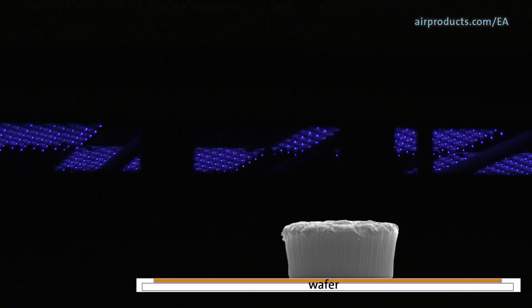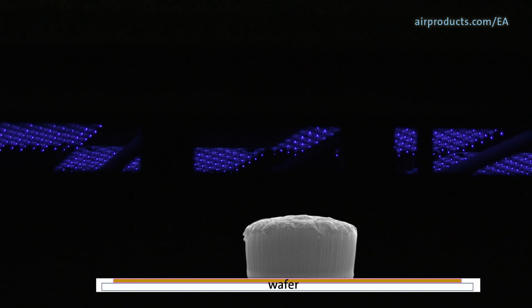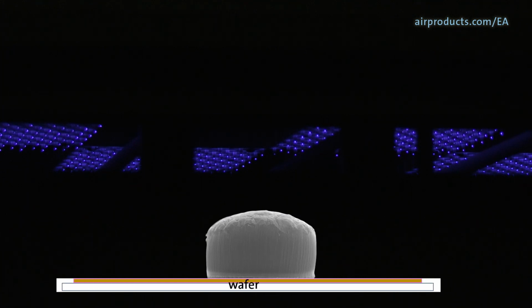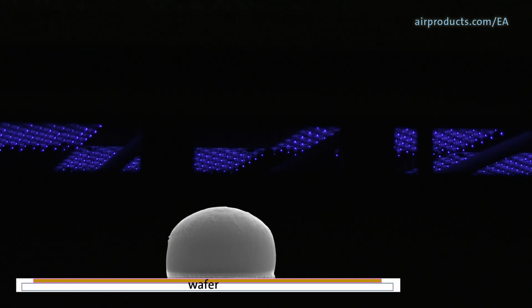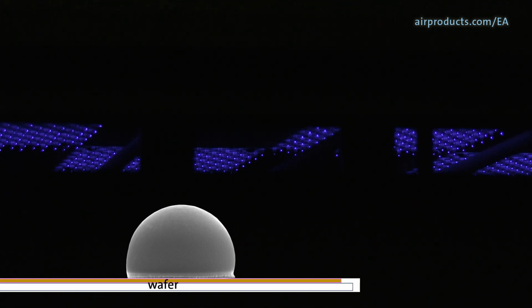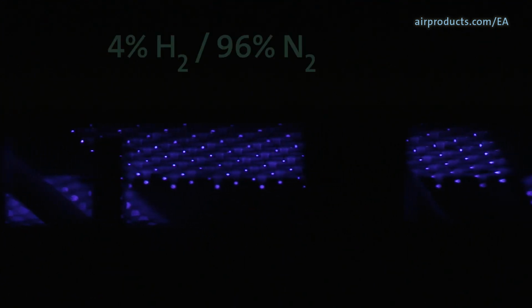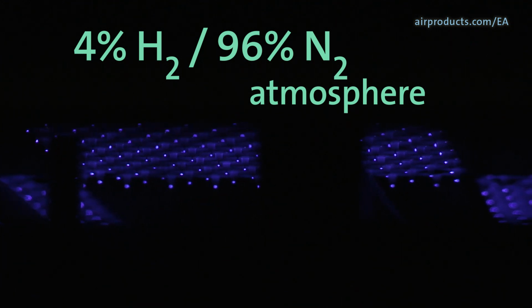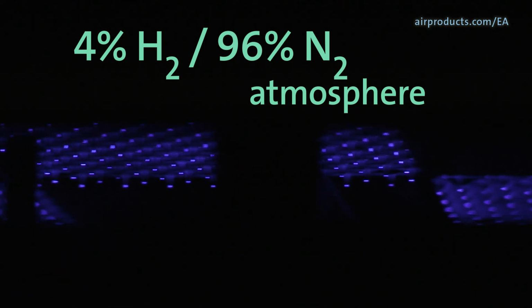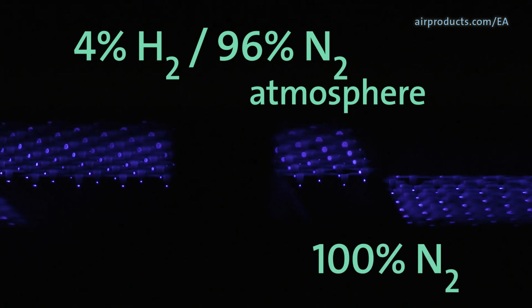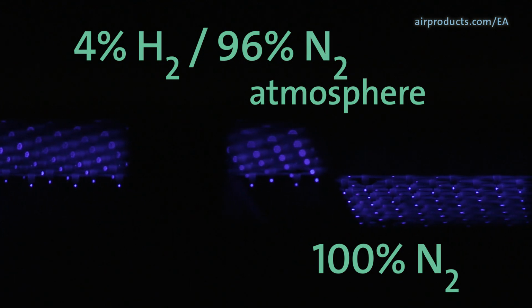As they travel along, first the metal oxide on the solder bumps is removed in the EA zones. Then the solder bumps will reflow to their proper shape in the reflow zone. The key to EA is the activation of the hydrogen gas in the gas mixture. The preheat, EA, and reflow zones have a 4% hydrogen, 96% nitrogen blended non-flammable atmosphere. The other zones have a 100% nitrogen atmosphere.